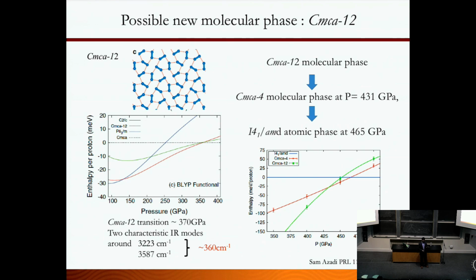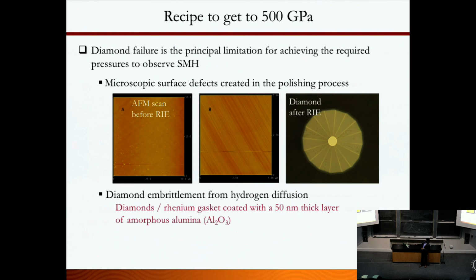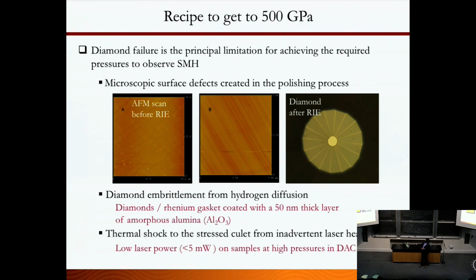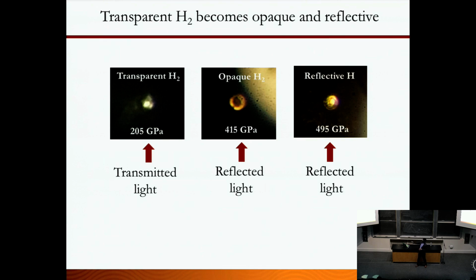On the other hand, you will not see it. So I'll show you this picture. In this picture, you have alumina right here. We put alumina on the diamonds, everywhere on the surface of the diamond. If you made alumina metal, you wouldn't see this kind of clear boundary between the diamond, the metal gasket, and the sample. The whole thing would be one shiny layer. You would not see the contrast in the material.